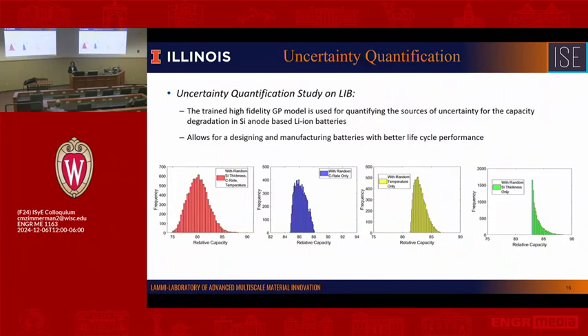So the first study we did is uncertainty quantification, with some initial assumption regarding the distribution of the input parameters, like the thickness and operation conditions. We can predict the distribution of the performance regarding each individual parameter or the collective influence of all parameters. And among that, we can identify which parameter is most critical in terms of the reliability performance of the battery.